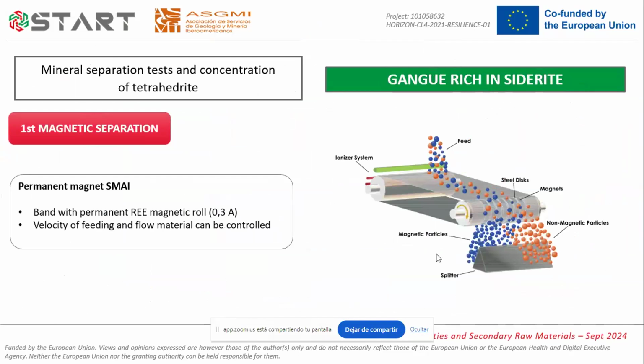The following step must only be applied to the samples with a gangue rich in siderite. A permanent magnet is the equipment, as I have mentioned, that we have used. It consists of a band with a permanent magnetic roll made of rare earth elements with an intensity of 0.3 amperes. Here we have a diagram of the way it works. The band is fed with the material. This material travels with the conveyor belt, and at the end there is a roll where the magnets are placed. So the magnetic material is attracted to the magnets and remains attached for a longer distance. The non-magnetic material falls first and is collected in a tray, while the magnetic material falls later and is collected in a different tray with the aid of a splitter. The velocity of the material feeding and the band can be controlled here.